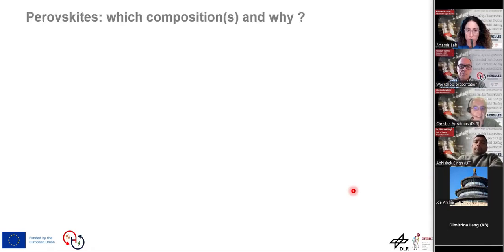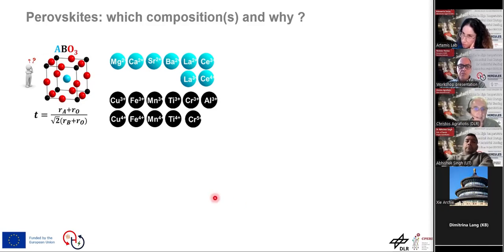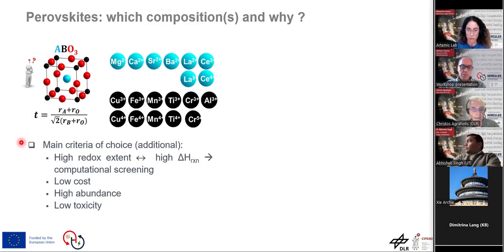Okay, so we chose perovskites then. How we select these A-B cations, we can see here, for instance, different cations that are bivalent and trivalent that are used in the first site: magnesium, calcium, strontium, barium, lanthanum, and so on. Or the second cation is transition metals like iron, manganese, and so on, which, if you can see, most of them have a double valence, and that's basically where the redox functionality is happening. Okay. And of course, not all oxides are compatible with all others. They have to have compatible radii, these cations that you can see there, in this Goldschmidt factor, which is a measure of the stability of this perovskite phase.